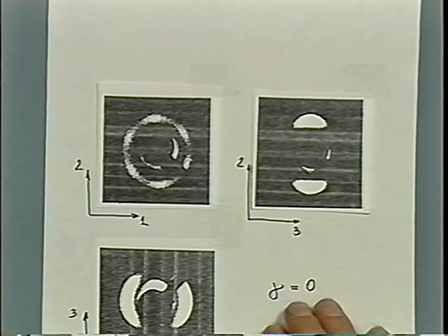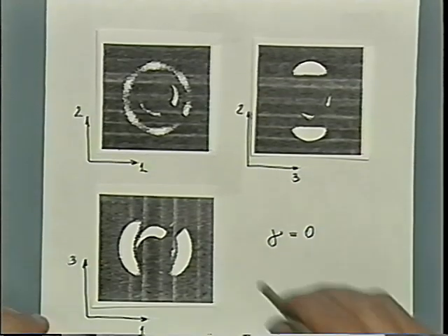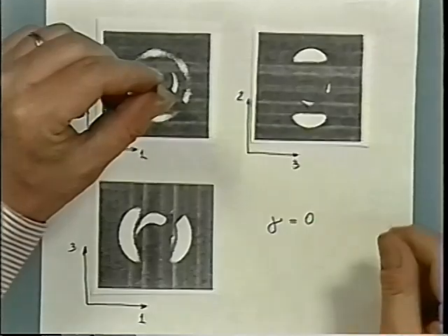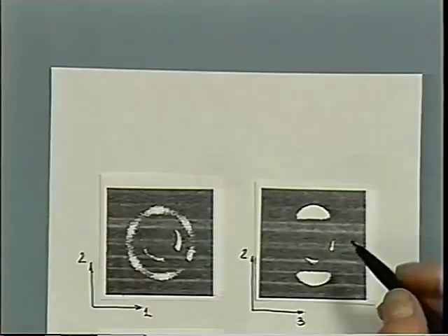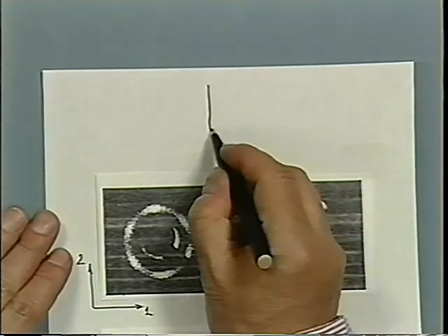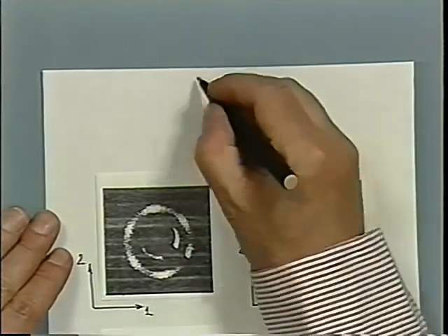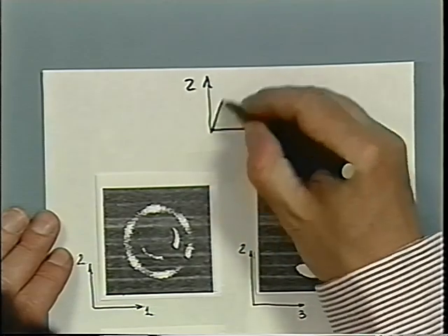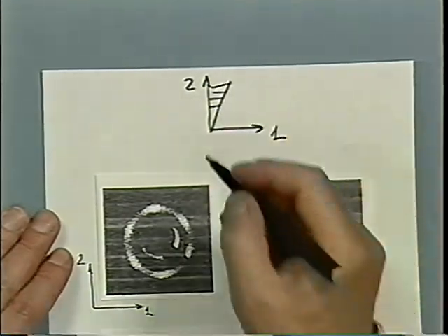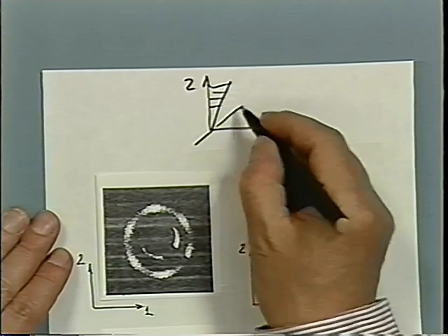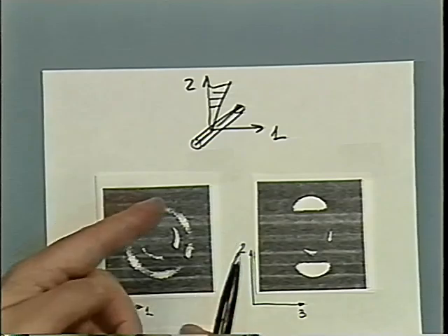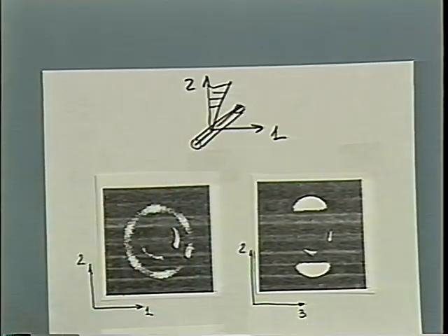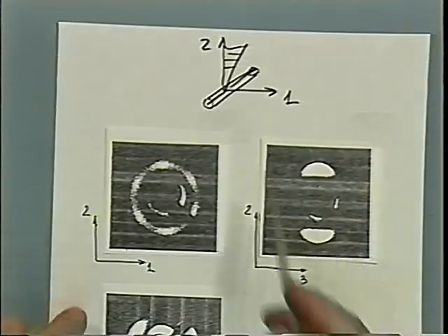And in fact, this is our initial sample. Remember, we had cylinders in the 3 directions. So here we are looking at 3 directions. Our coordinate system for this observation is something like this. We have our 1 direction. We have our 2 direction. This is the shear flow which we are going to impose. And this is our 3 direction. And this is the direction where our cylinders are aligned with a hexagon pattern. So we are looking at our object here.